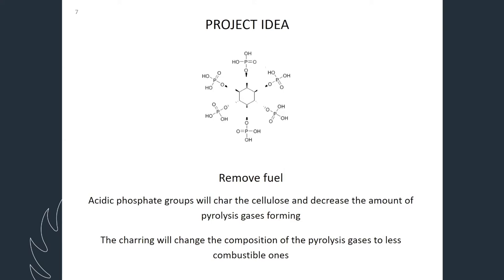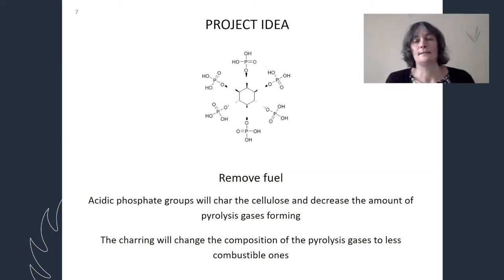So the idea is then that with this flame retardant, we can remove the fuel, because when this phytic acid molecule breaks down when it's heated, it will form phosphate groups. And phosphoric acid is an acid, and acids char the cellulose. So that will lead to a decreased amount of pyrolysis gases, less fuel. And this charring, when it's happening at a lower temperature, will change the composition of the pyrolysis gases. So the ones that form will be less combustible than the normal mixture without the flame retardant.